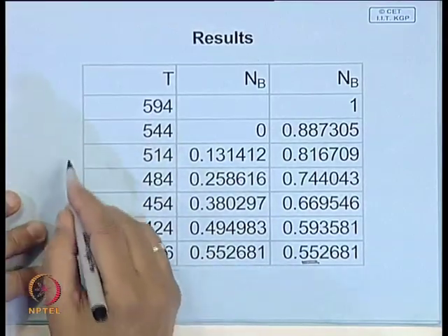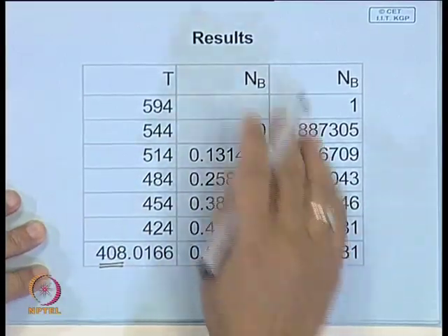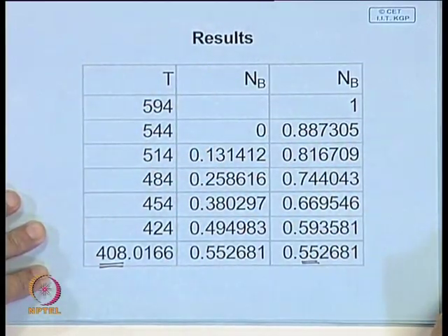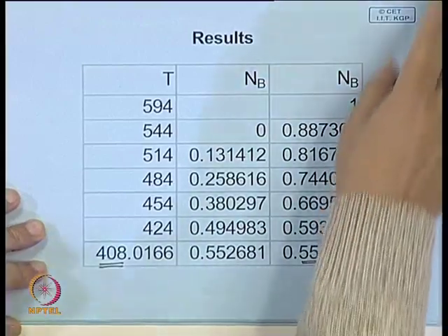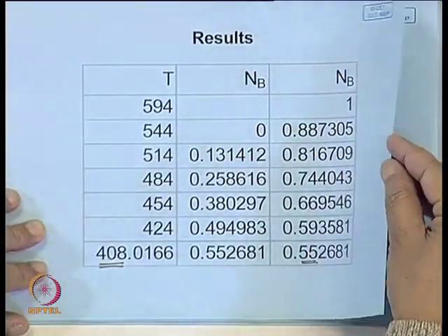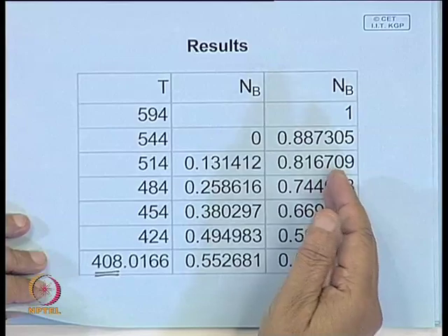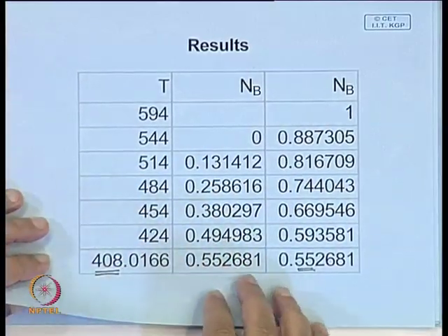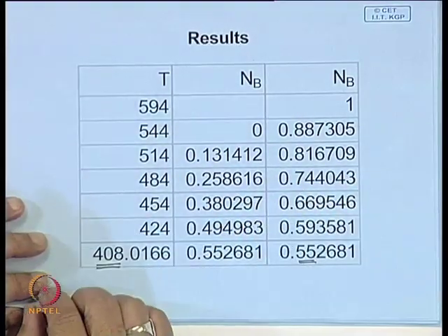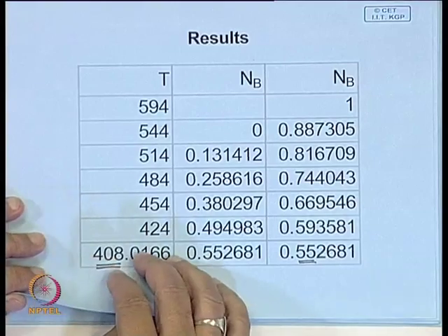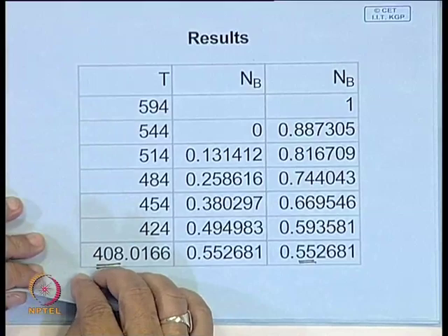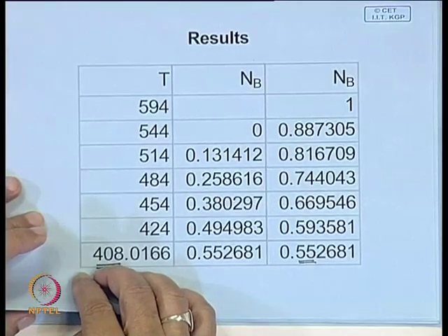So, that means you have to question these assumptions, but this is a procedure which is applied, and in one way you can say that thermodynamic properties are also evaluated from the phase diagram. Experimentally you determine it, and then you try to conclude whether that liquid solution is ideal or not. If it is not ideal, from this it is possible to calculate how much its deviation from ideality is.